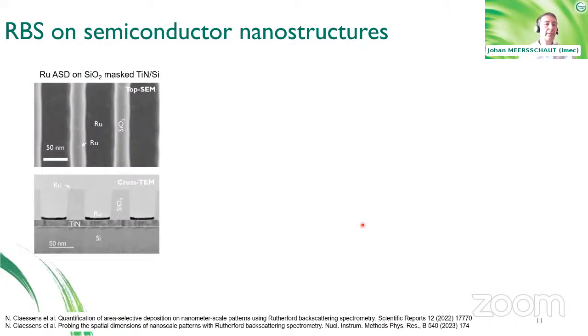So how can we use this technology in practice? How can we use the energy loss of ions in matter to our benefit? And here I use an example of studying nanoparticles of the order of or less than 50 nanometer high, built of silicon oxide, which are grown on a titanium nitride buffer layer. And in the microelectronics industry, there is a lot of effort going on in area selective deposition to aid lithography to have better nanostructures, helping to make smaller devices for the microelectronics industry.